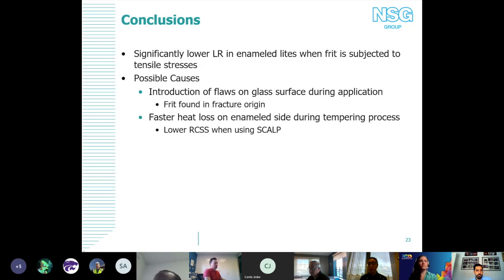And another thing may be that you're getting more heat loss on the enamel side during the tempering process. So potentially by adjusting the tempering process, you can create a more even residual compressive surface stress, but a lot more work needs to be done on that in order to see if that's even possible or a plausible thing to do. So really, next slide, Kate.